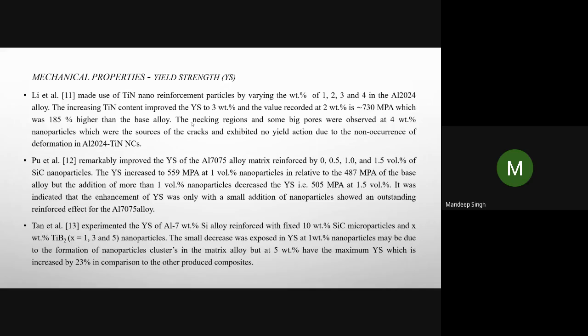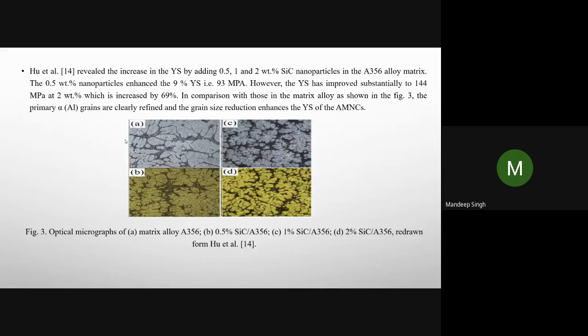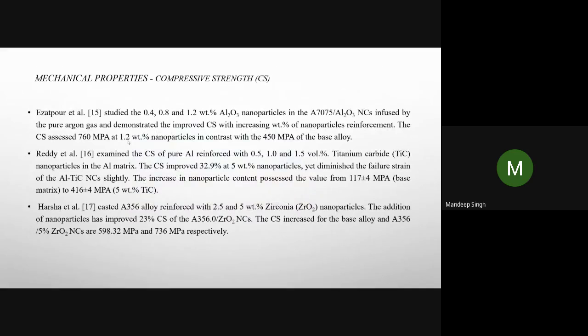So the reason is that necking regions and some big pores were seen at 4 wt.% nanoparticles, which become the source of cracks and show no yield action due to the non-occurrence of deformation of Al2024-TiN nanocomposites. Then the next mechanical property we have is the compressive strength.